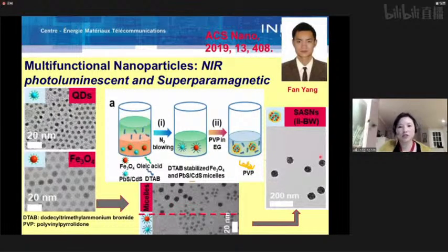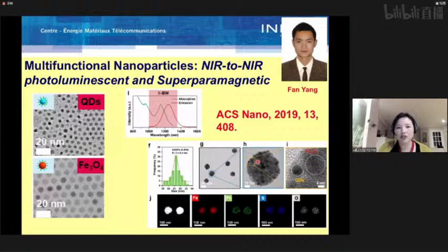And then this excellent student combined quantum dots with superparamagnetic iron oxide particles, quantum dots about 5 nanometer, iron oxide nanoparticles about 10 nanometer. We used a self-assembly approach. Due to limited time, I will not go into the details, but we can get uniform multifunctional nanoparticles. In each particle there are many quantum dots, many superparamagnetic particles, and from elemental mapping, we can see iron, lead, sulfur, oxygen are uniformly distributed in these single nanoparticles. By the way, these assembled particles are about 60 nanometer in diameter.